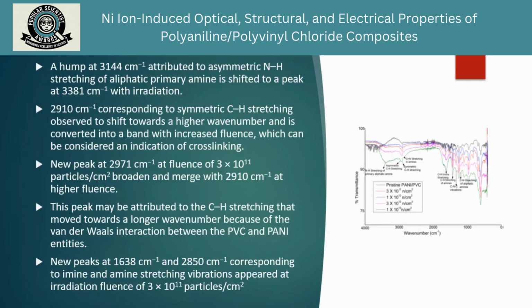The next study was about FTIR spectra to study the structural changes in the material with the nickel 7+ ion beam. It has been observed that a hump at 3144 centimeter inverse may be due to asymmetric NH stretching of aliphatic primary amine, and it is shifted to a peak at 3381 centimeter inverse with irradiation. Another peak at 2910 centimeter inverse, corresponding to symmetric CH stretching, is observed, and it has shifted to a higher wave number and converted into a band with the increased fluence, which can be considered an indication of cross-linking.